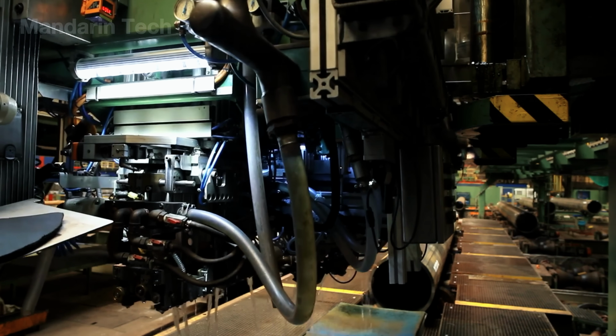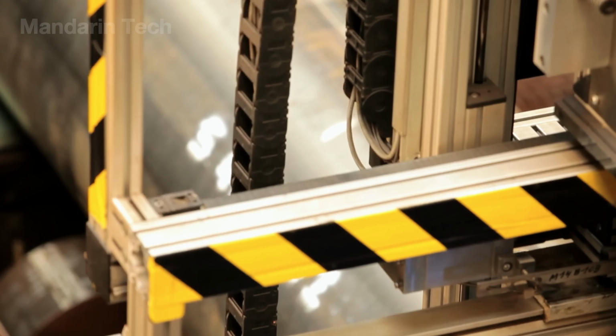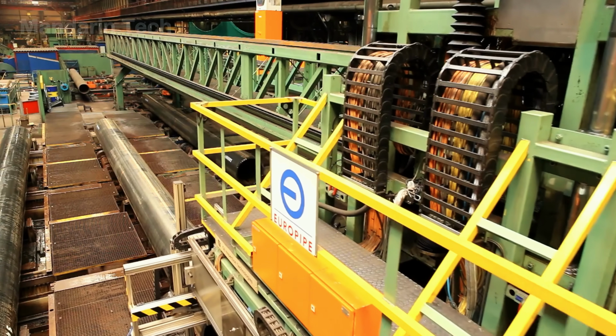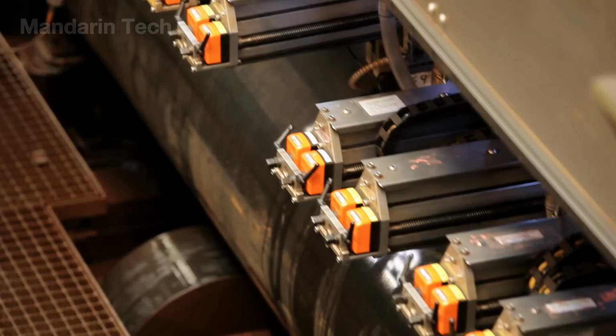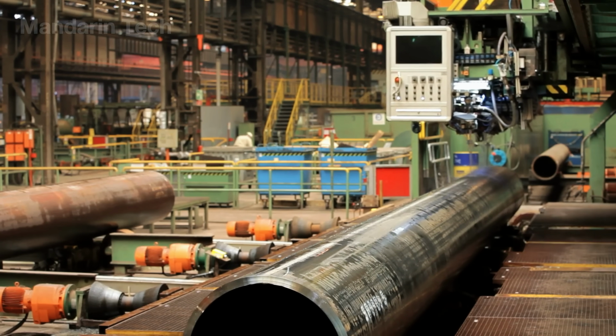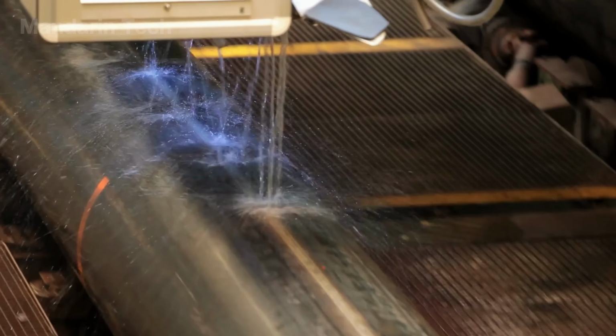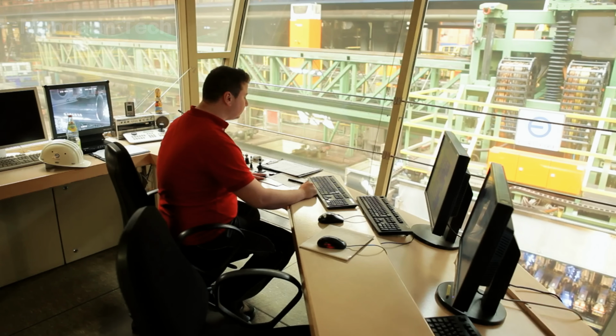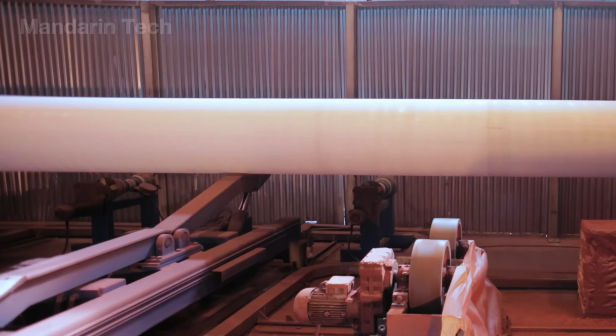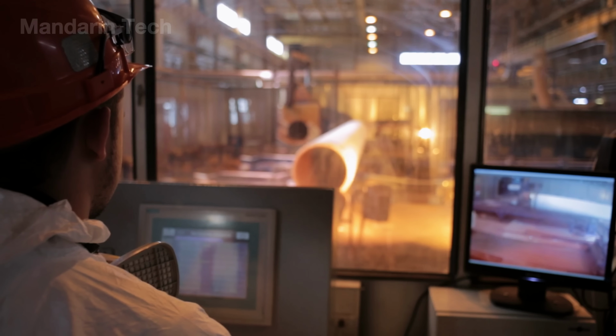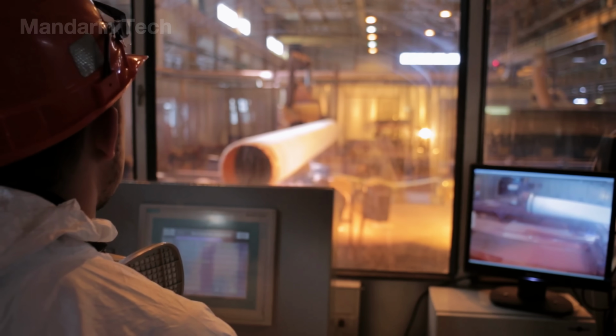After that, the weld quality is inspected using ultrasonic testing and hydrostatic testing. Both the pipe body and the weld must withstand pressures of over 420 atmospheres, which is about 1.5 times higher than the maximum expected operating pressure of the future pipeline. At this stage, the product is almost ready for transportation.